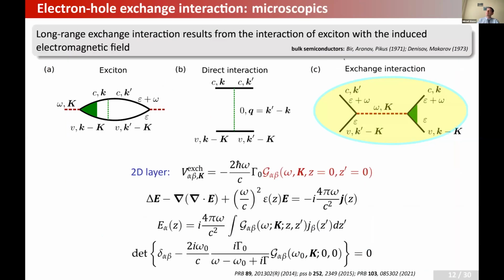You can do another calculation. You can take into account that the exciton is like a dipole. It produces an electromagnetic field, and then, as any dipole, it interacts with the induced electromagnetic field, and it will actually give the same result. You can make it using the Green's function technique. You can do it using Maxwell's equations, and so on and so forth. You can do it diagrammatically, for instance, and you can calculate this contribution to the exciton energy related to the process I have described: virtual recombination, virtual annihilation of the exciton, and generation of an exciton in the other valley or with different spins.